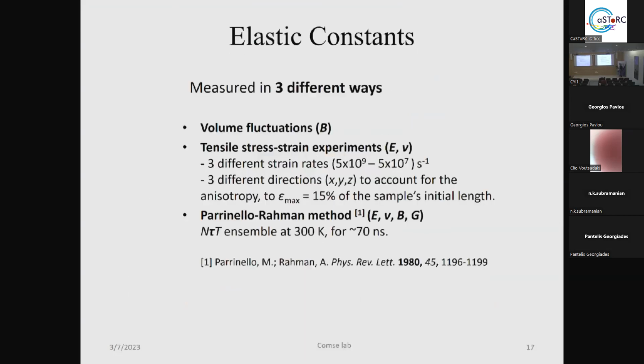As you can see, we did it with three different strain rates, from 7 to 9 in second^-1. So we took these three strain rates, but we saw that we estimate on the 10 in order of 8. So the answer is 10 in the order of 8. But we did it with three different rates.